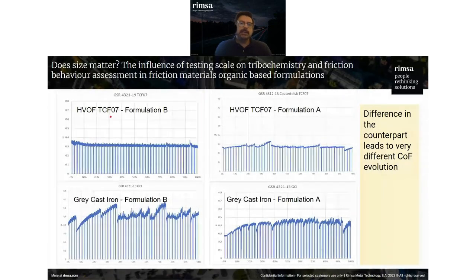dynamometer. And this is the same case for, you can see here, if we use a different formulation, or we can compare different formulations with different rotors. In this case we have here a hard-coated rotor with titanium carbide and with a formulation B. And you can see how the formulation B with the same rotor behaves in a different way, and how they compare with a gray cast iron. This is completely different in a gray cast iron and in a hard-coated rotor.